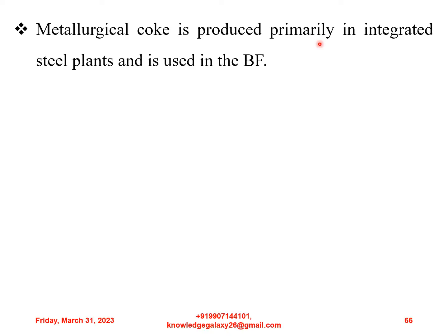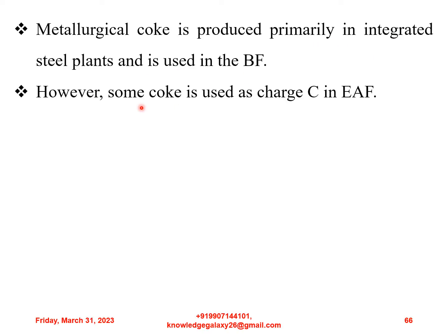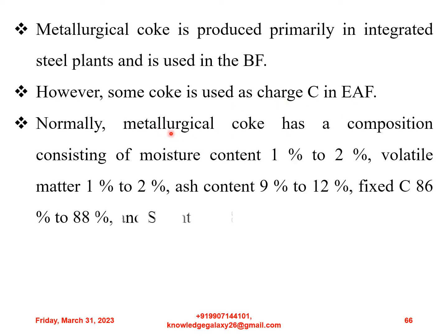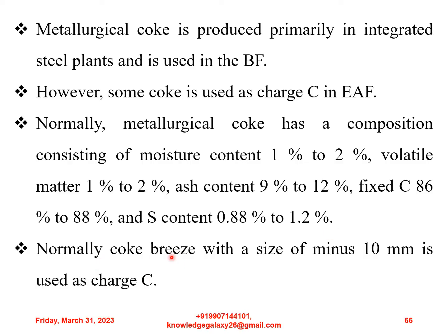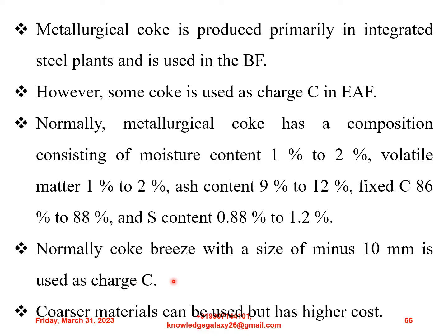Metallurgical coke is produced primarily in integrated steel plants and is used in the blast furnace. However, some coke is used as charged carbon in electric arc furnace. Normally, metallurgical coke has a composition consisting of moisture content 1 to 2%, volatile matter 1 to 2%, ash content 9 to 12%, fixed carbon content 86 to 88%, and sulfur content 0.88 to 1.2%. Normally, coke breeze with a size of -10 mm is used as charged carbon. Coarser materials can be used but have higher cost.